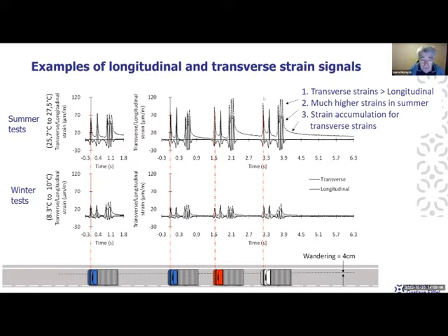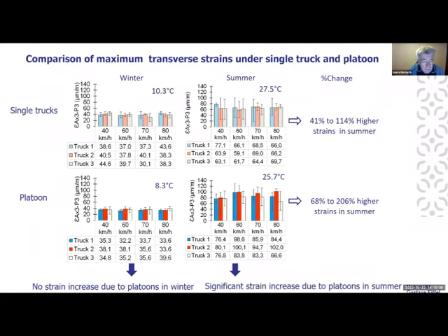And we also found that for our test, the transverse strains were higher than the longitudinal strains. So because we were interested mainly in the maximum strains, we looked mostly at the transverse strains. So first, just a comparison of the measurements. Here you have the maximum strain amplitudes observed under a single truck and under a platoon in the winter conditions on the left and in the summer conditions on the right. And so you can see that in the winter, with temperatures around 10 degrees, where the behavior of the pavement is more or less elastic or where the viscoelastic effects are reduced, you have practically the same strain levels under the single trucks and under the platoon.